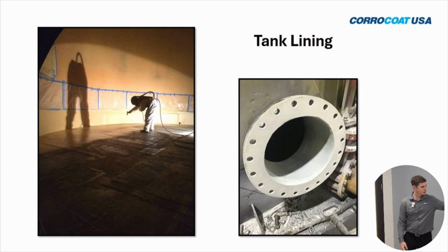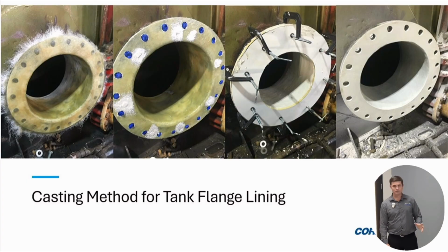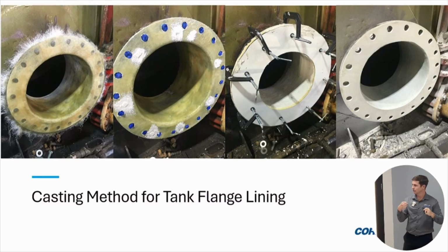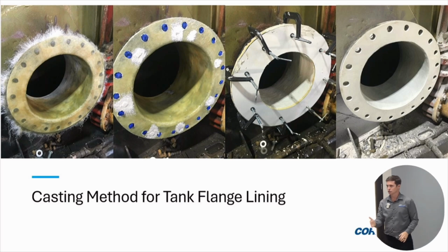You can see this flange here, it's finished flat. We have a better method of dealing with a flange, but in situ, on a big flange like this, it works pretty well. So you see we'll fiberglass it out. We make free film samples with the coating. We use those as shims. We essentially glue them to the substrate here. Then we clamp down a piece of laminar board. Wait about 4 hours, you pull it off, and then you get a flat flange. It's much more effective. It leaves a flat finish, plus or minus 0.005. Easy to go onto, particularly with a soft gasket, and it's done.